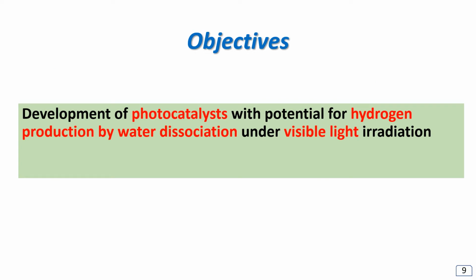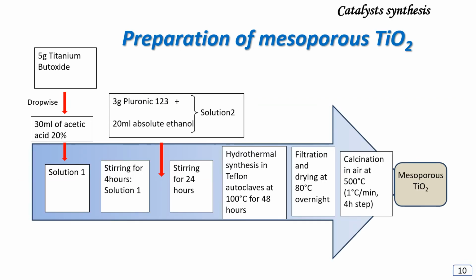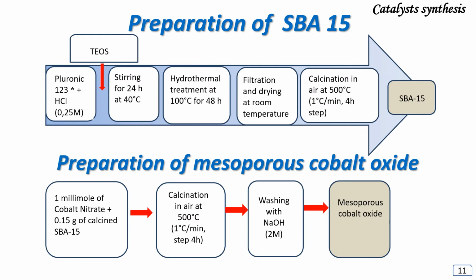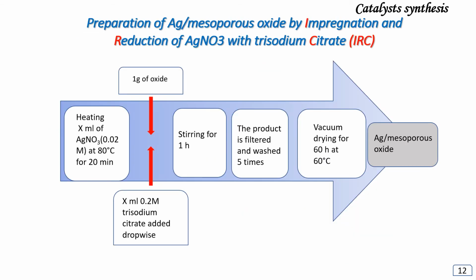The objectives of this work are the development of photocatalysts with the potential in the production of hydrogen by dissociation of water under visible light irradiation. Titania was prepared by soft template method as indicated. SBA15 was also prepared by soft templates. Cobalt oxide was prepared by hard template as shown in this scheme. Silver doping was done using a simple method called impregnation reduction by trisodium citrate.